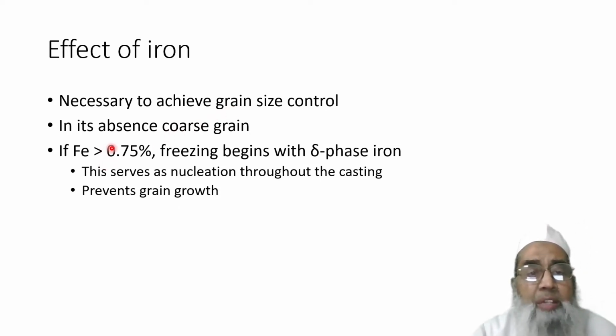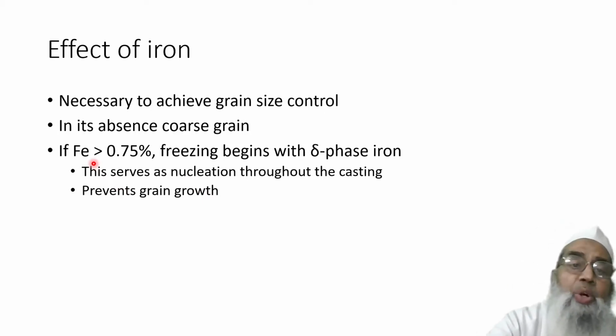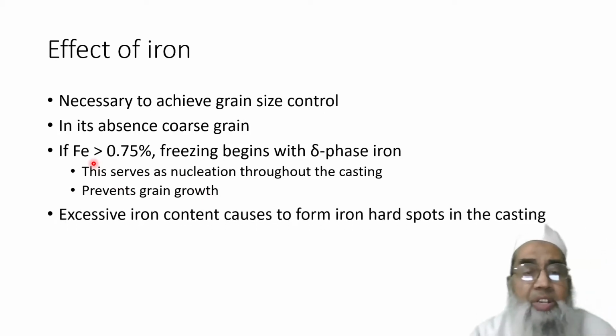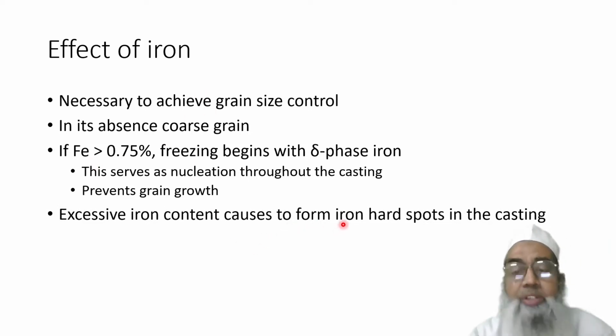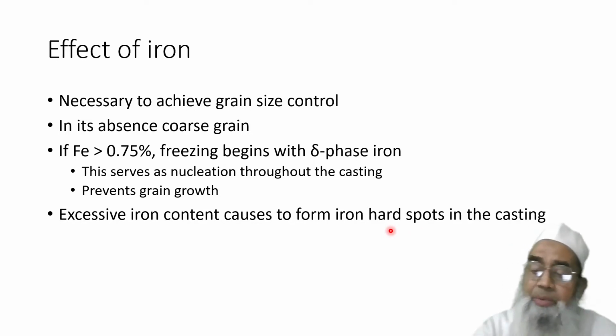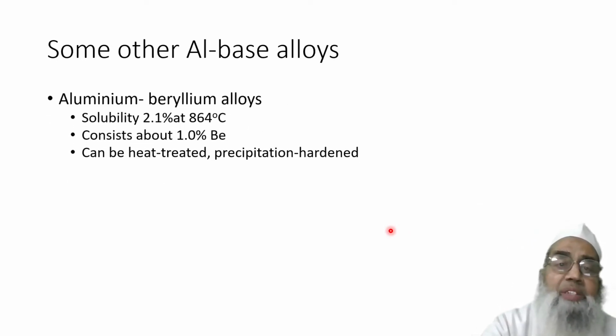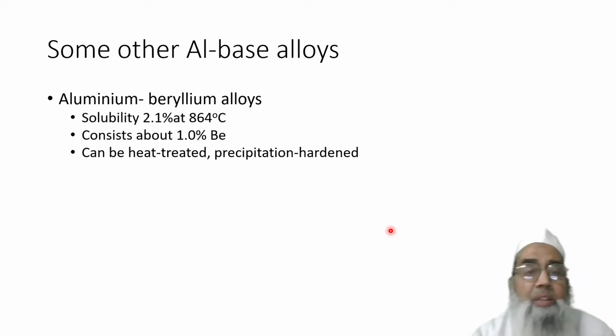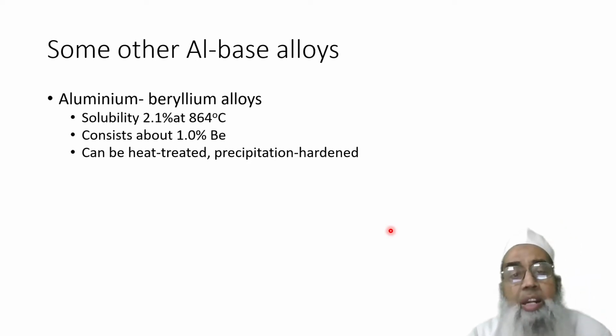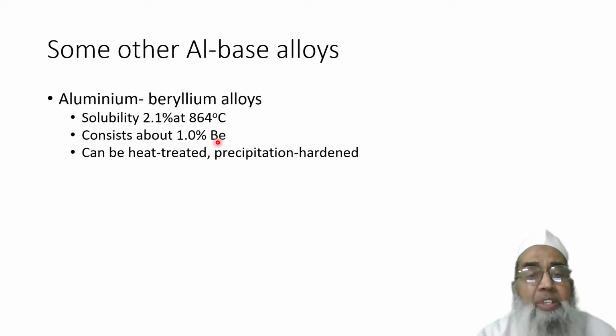If more than 0.75% iron is there, then freezing begins with delta phase iron. This serves as nucleation throughout the casting, and therefore prevents grain growth, and we can control the grain size. Excess iron content causes iron hard spots in the casting, and therefore machining becomes difficult. Some other alloys like aluminium beryllium, which is soluble 2.1% at 864 degrees centigrade, consist of about 1% beryllium. It can be heat treated, and precipitation hardening can be done.